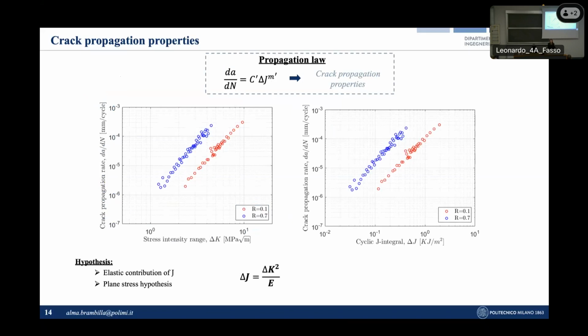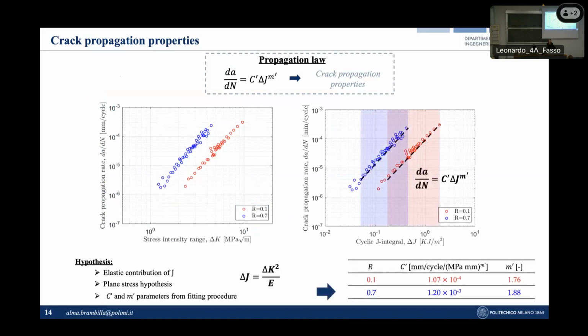So once having the evolution of the crack growth rate as a function of the cyclic J integral, by fitting the data with the modified Paris law, the crack propagation parameters C prime and m prime were obtained for the two load ratios.